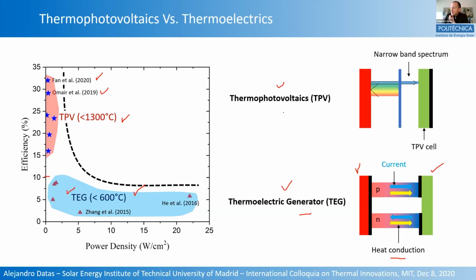Well, the strategy in thermophotovoltaics is completely different. Here you have a possible arrangement where you have the hot emitter and the photovoltaic cell, and you place a filter in between them. Also, you could use a backside reflector, as Andrej commented in his presentation. But the aim at the end is to have a very restricted spectral band of emission that is reaching the cell. So the net radiative transfer between the emitter and the cell is restricted to a very narrow range of energy photons. So it reduces quite a lot the power density, but it enables to use high bandgap materials.